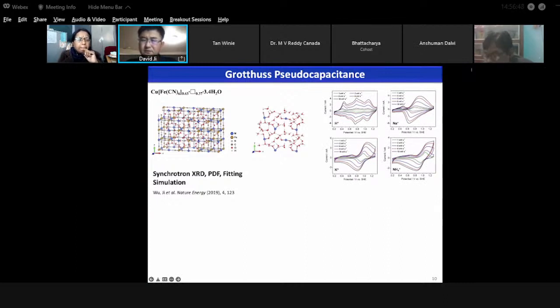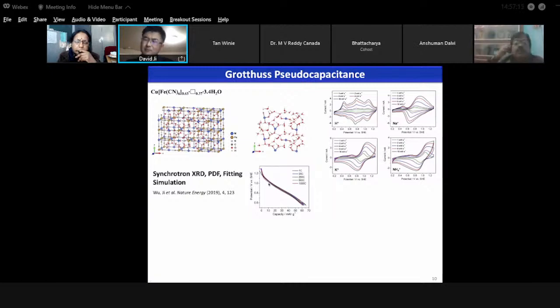And it turns out that it's pretty impressive in terms of the kinetic reversibility. The kinetic reversibility for proton. The same electrode doesn't have that behavior for sodium, for potassium, for ammonium. But for proton, you have the kinetic reversibility. That's quite interesting. And the active mass loading of this electrode is around 2 to 3 milligrams per square centimeter. Yeah, so it's not too light, I would say.